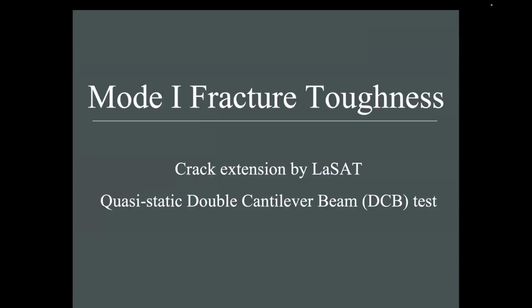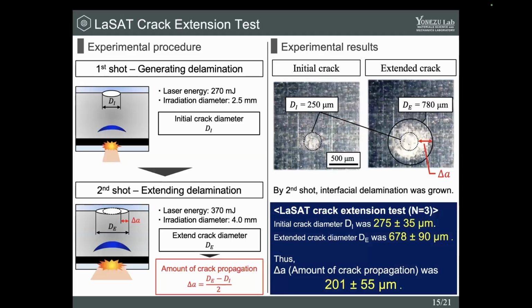From this slide, I'd like to talk about mode 1 fracture toughness. To evaluate impact of fracture toughness, we conducted LaSAT crack extension test. This is the experimental procedure. At first shot, we generate an interfacial delamination and measure initial crack diameter, DI.